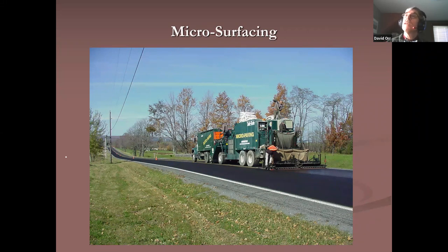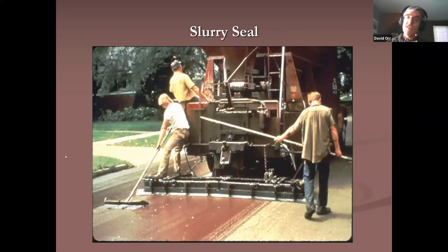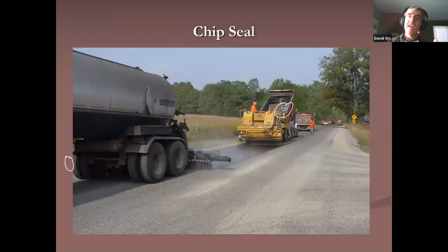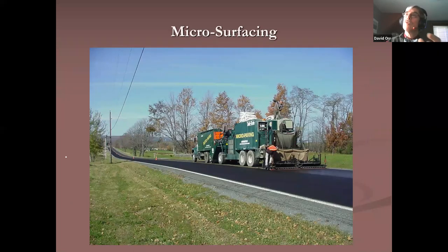Somebody asked a question, what are your opinions now that polymers are available for oil and stone? Well, again, much in the same way that a slurry seal is good for sealing the surface, a micropaving gives you a little bit of additional benefit with the polymer. There's some things you can do with it. The polymers give you some different situations you can use them in. Plus, they can increase the ability to handle different weather extremes. If you're in the North Country, for instance, I would think about polymers. If you've got a lot of traffic, think about polymers. But you've got to look at the cost benefit. If it's a couple of percentage points more, almost always worth it. You start getting more than that, you've got to look at the situation, okay? I like polymers if they're used properly, okay?